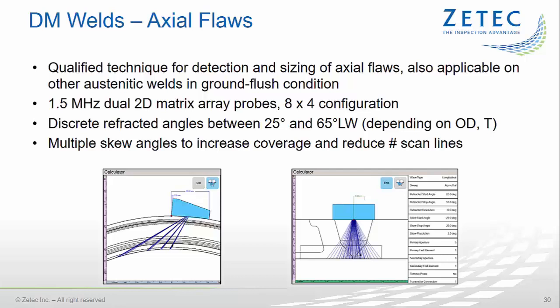The wedge assemblies are designed to allow for the generation of L-wave beams with several refracted angles between 25 and 65 degrees, with adaptable increments, and skew angles from -20 to 20 degrees, with typical increments of 2.5 degrees. This results in a total of approximately 80 acoustic beams being fired at each search unit position. The images on this slide show the visual representation of this inspection technique in the calculator.